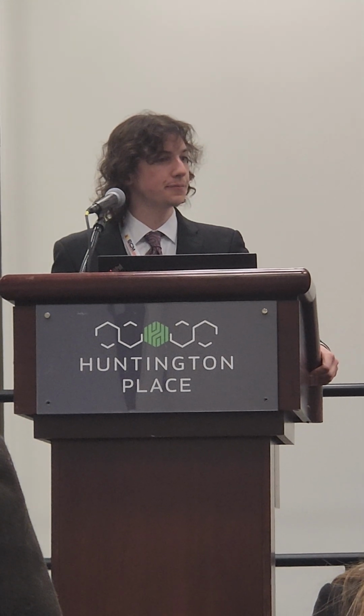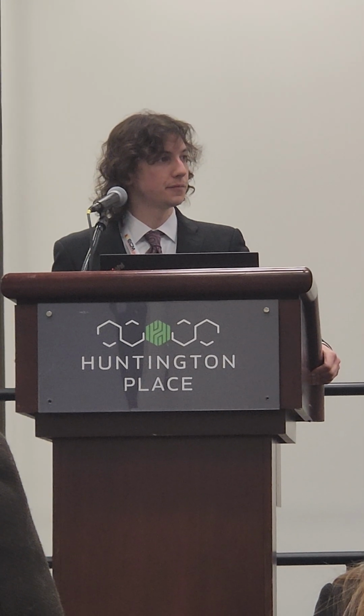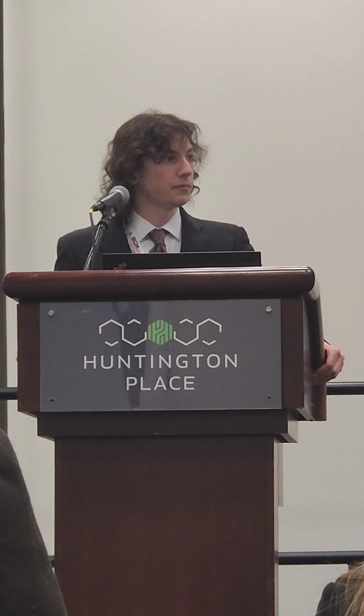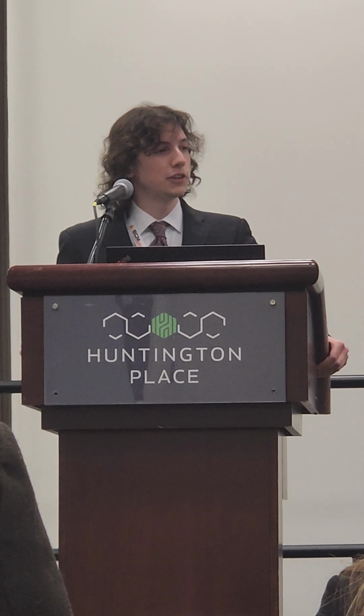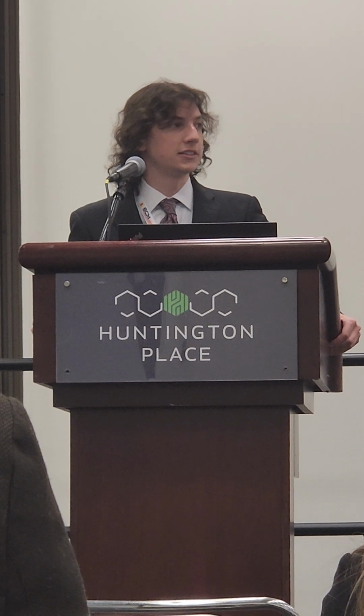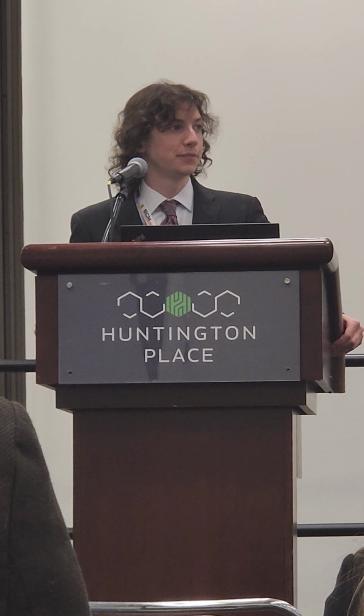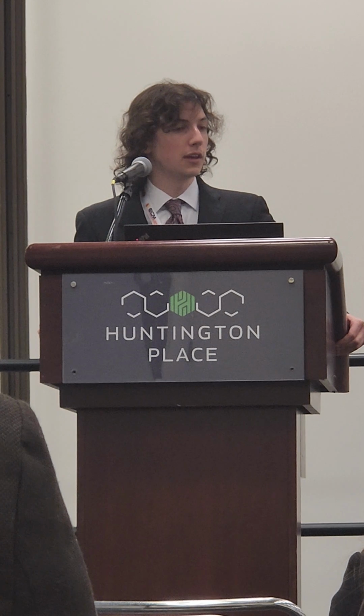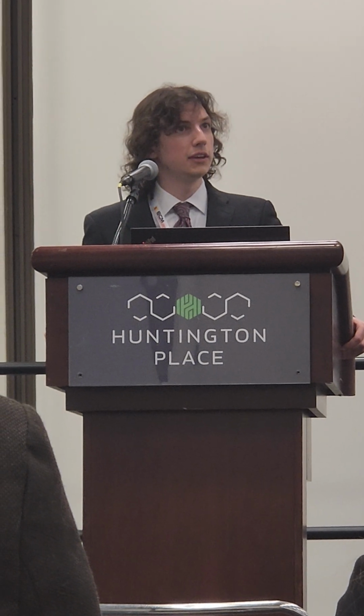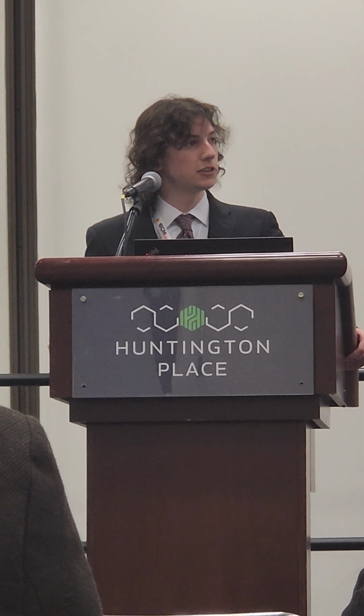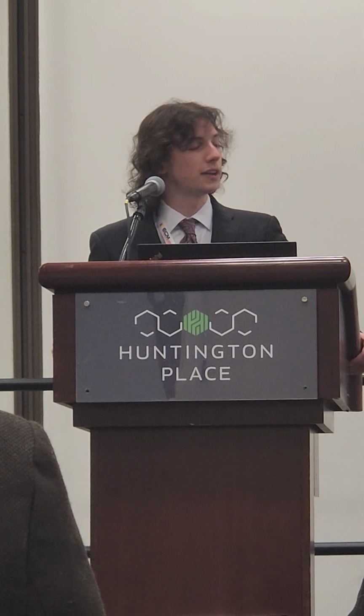Okay. Do you understand there's any decarb at that point when you remove those samples? Yeah, there is decarburization, but all these are taken from far enough within the surface that you're not seeing that decarburization microstructure. How big were the samples? Maybe 5 millimeters, like 25 square millimeters.